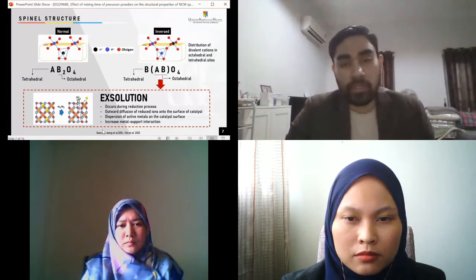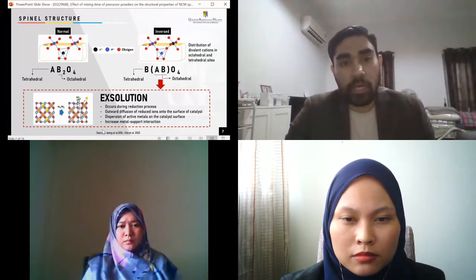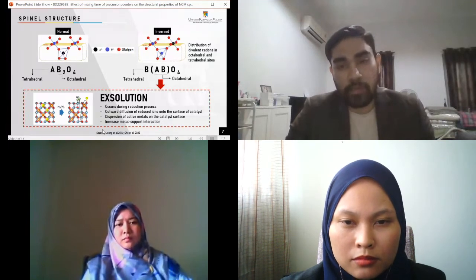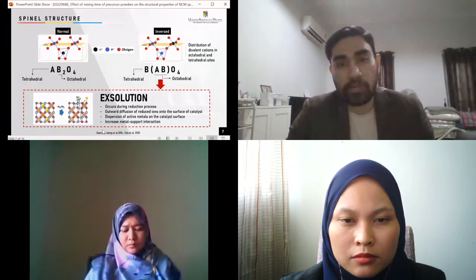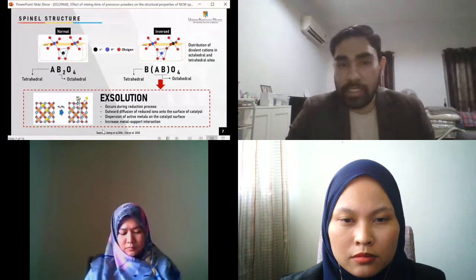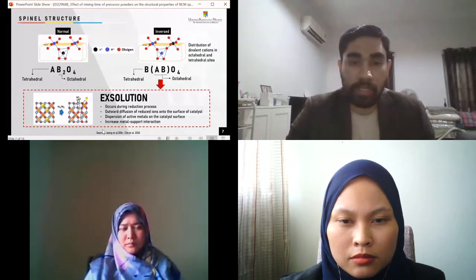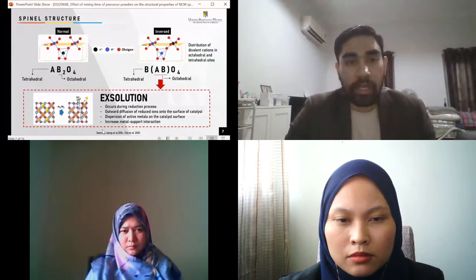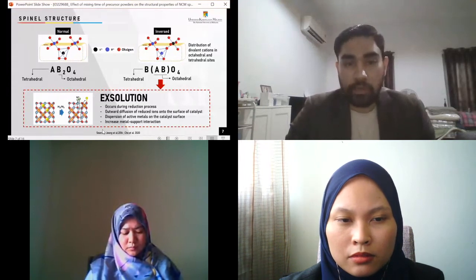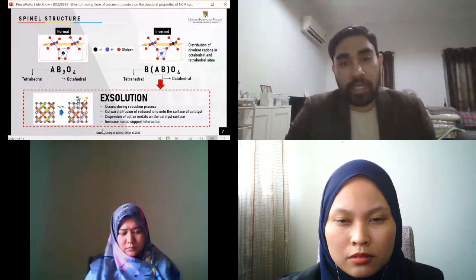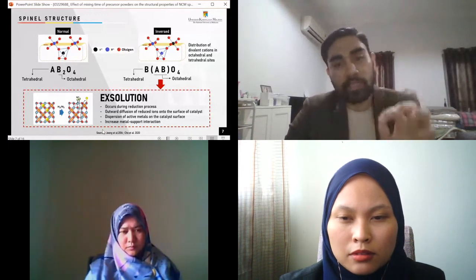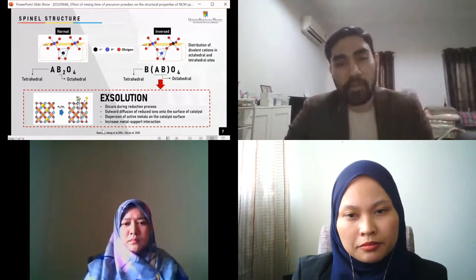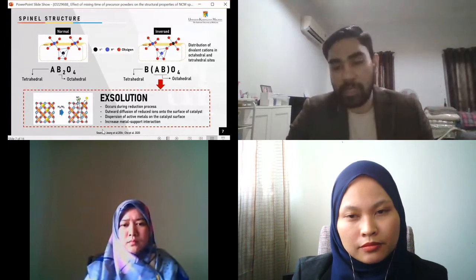When the exsolution occurs, it allows the outward diffusion of reduced ions from the active metal onto the surface of the catalyst. This helps in the dispersion of active metals on the catalyst. And by having this structure, it is expected to increase the metal support interaction, increasing the chemical stability of the spinel for long-term operation for methane reforming.